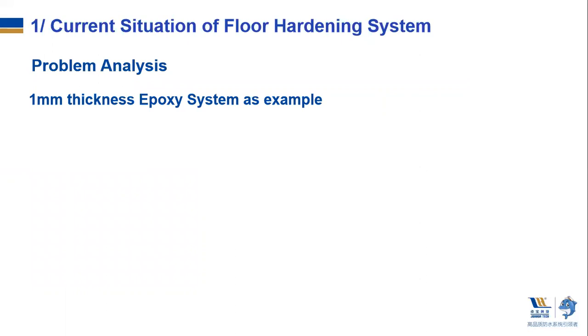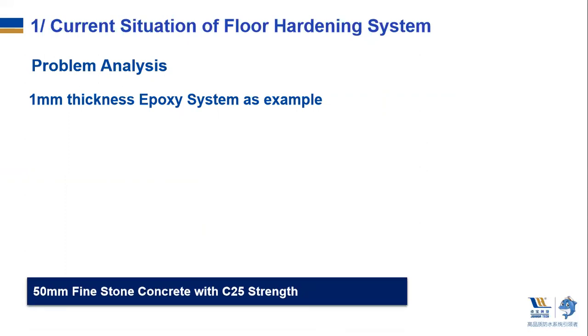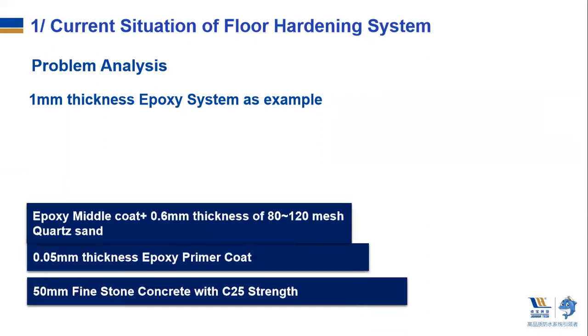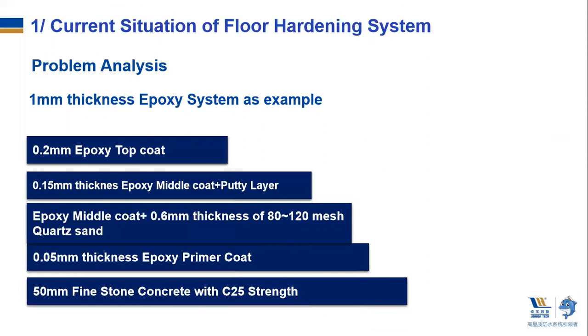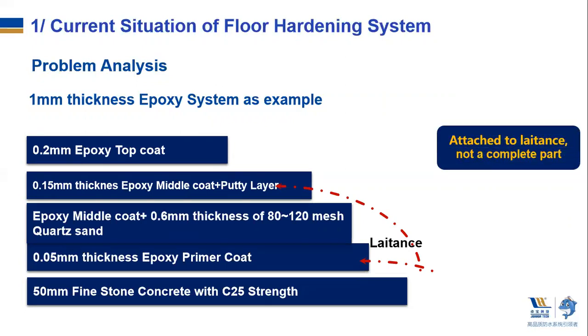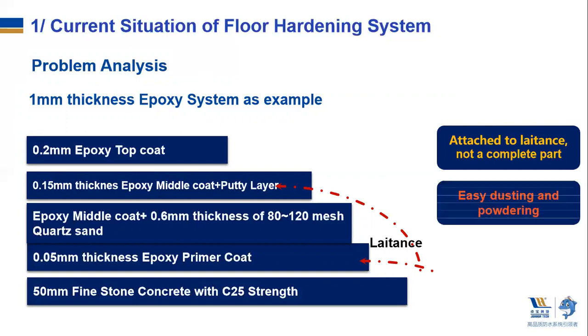We can review this design and infer that epoxy coatings has many layers and each layer is different in materials and physical performance. The primer coat, middle coat, putty, top coat are actually not an integration layer because the adhesion between the system and the substrate is only achieved by the primer coat. Moreover, the whole system is connected with the laitance, a floating layer of concrete with low strength. After long time traffic and self-aging, the laitance will have powdering problems and thus resulting in hollowing between laitance and the whole system.